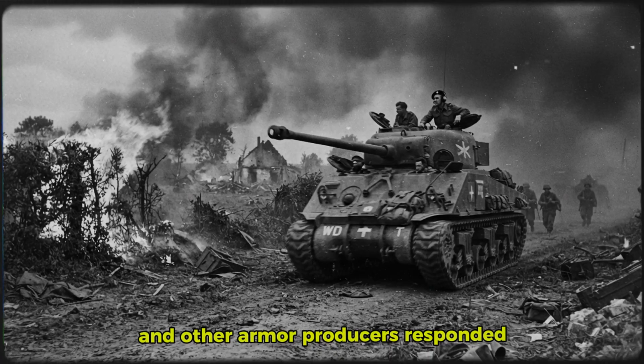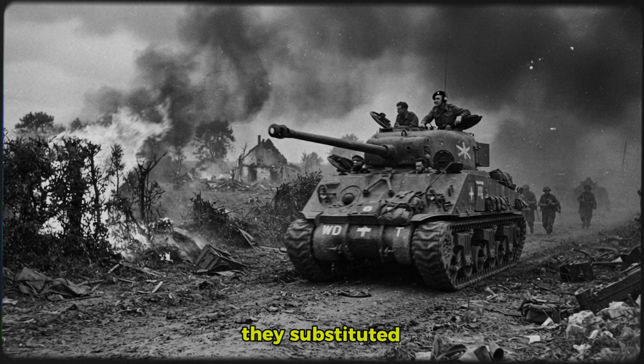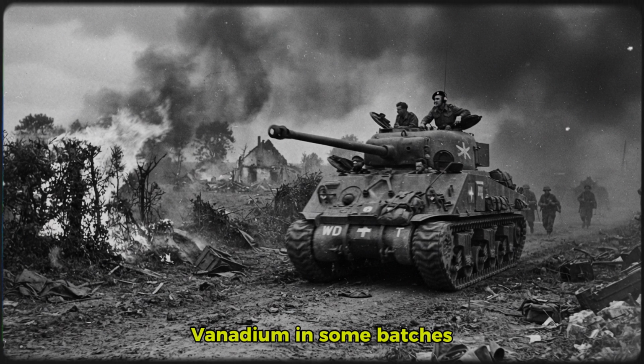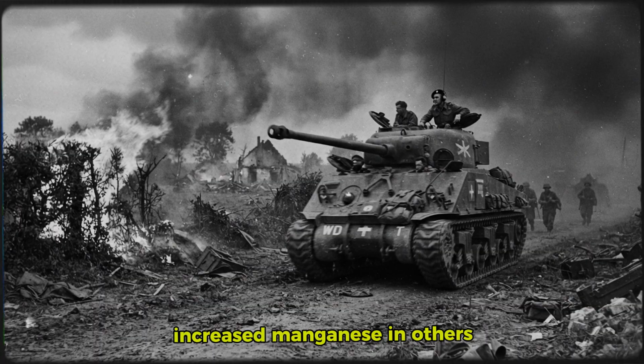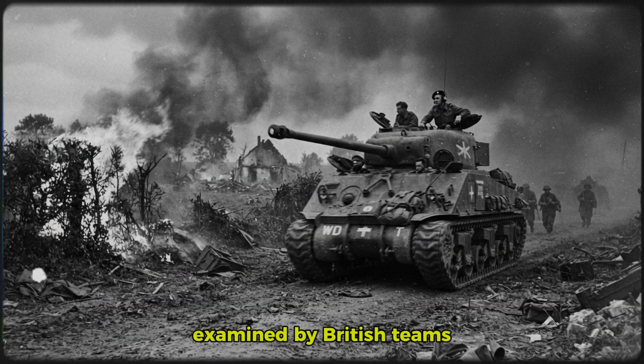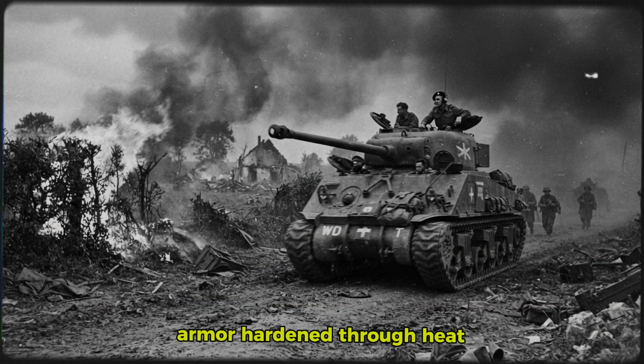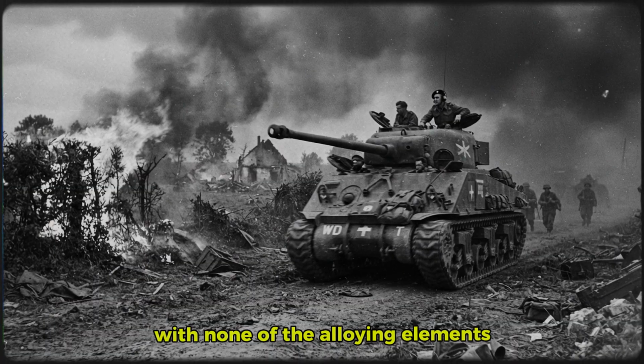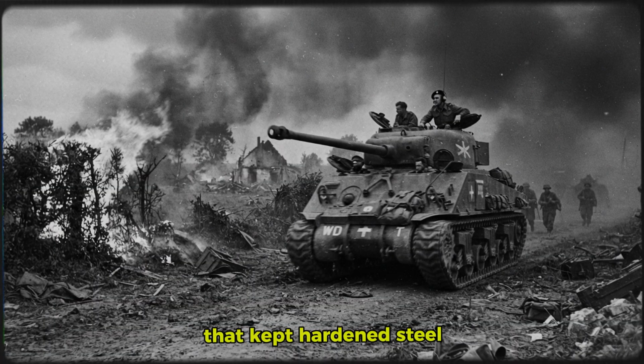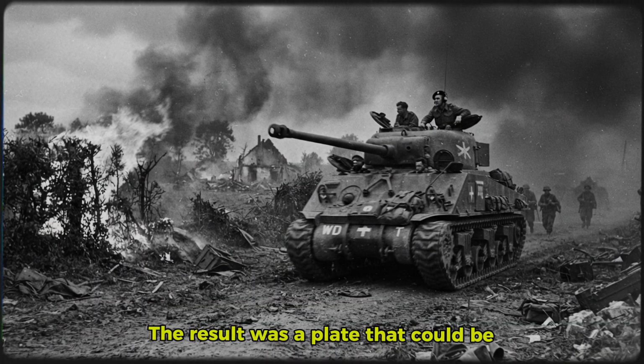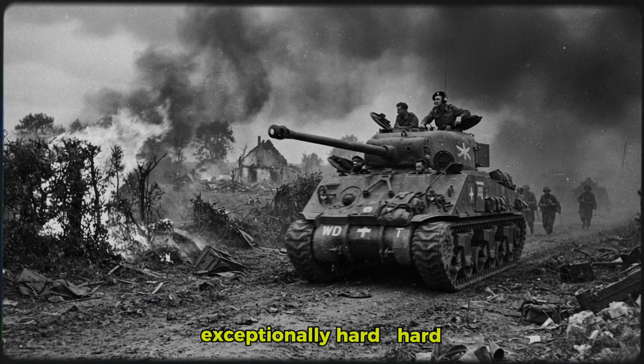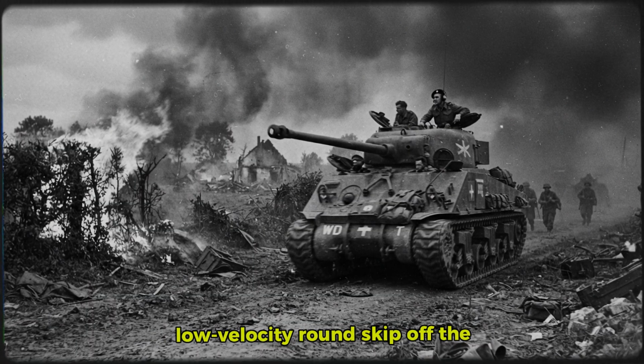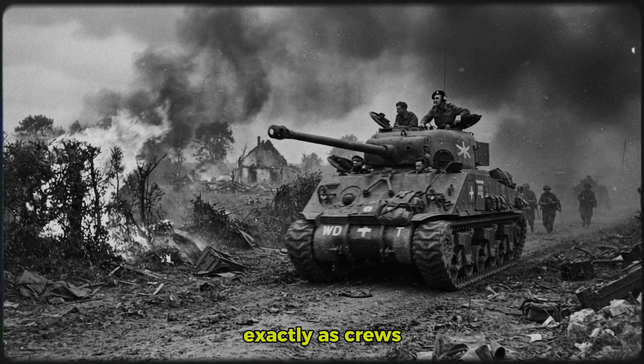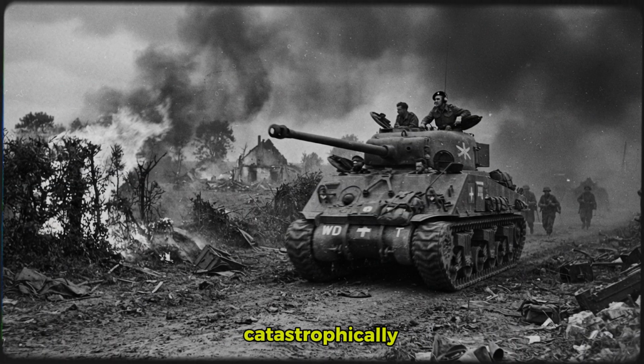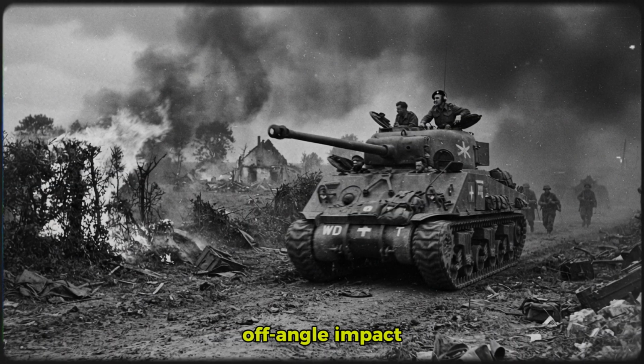Krupp and other armor producers responded the only way they could. They substituted. Vanadium in some batches, increased manganese in others, and in the worst plates examined by British teams, next to nothing. Armor hardened through heat treatment alone, with none of the alloying elements that kept hardened steel ductile under shock loading. The result was a plate that could be hard enough to make a low-velocity round skip off the surface entirely, exactly as crews reported, while being catastrophically brittle under repeated or off-angle impact.